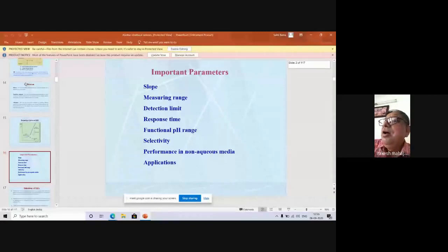The next is the functional pH range. You know, the pH plays an important role in the measurement. If pH is changing and potential is also changing, then it is not good, because we should have a pH range in such a way that the range should be very wide, and in that pH range there should be no change of the potential. The potential should remain constant within that range. If the potential is also changing with the pH, then there is no use of having that membrane.